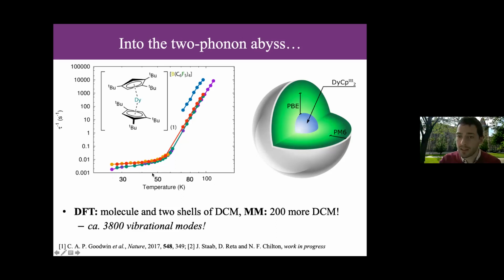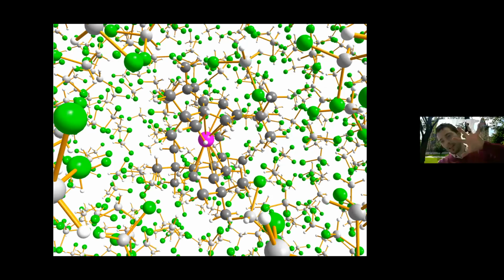We went away and did these sort of QM/MM calculations, where you have a layer of solvent described by real density functional theory, so molecules and basis sets and things, and then a semi-empirical or molecular mechanics model on the outside, where you have a bunch more DCM. And so a lot more effort computationally to find the vibrational modes of this chunk. And so we have about 3,800 vibrational modes for this particular problem. This is a picture of what it looks like from the inside. You have a molecule inside lots of solvent, and we're calculating all the possible vibrational modes of this.